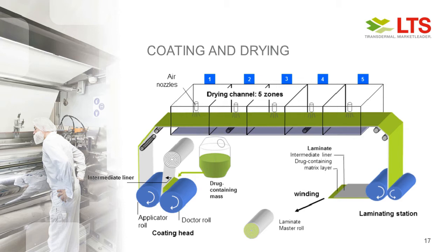An intermediate liner, which is the substrate for the coating, is pulled through this coating head, and by the gap between these two rolls, we can simply dose the drug-containing adhesive mass to a certain thickness. Of course, wet, still containing the solvent. This coated adhesive mass is then transferred on the liner into the drying oven, which in this case consists of five different zones. We can set up a distinct drying profile to achieve, at the end of the drying oven, a dry product, a dry film in a certain width.